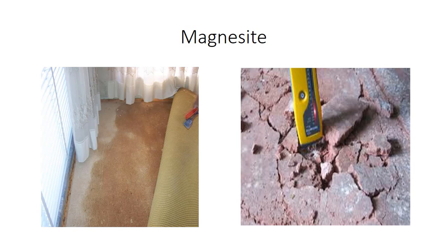One of the problem subfloors you may come across from time to time is one called magnesite. Magnesite is a very strange material. It has wood chips in it. One of the disadvantages of the wood chips in it is obviously if you cover it over, as you can see by the picture on the left, that's only just the carpet. What can happen is the material can soak up moisture from the air, and from underneath. It will start to swell and it will start to break up, which is what the picture on the right shows.